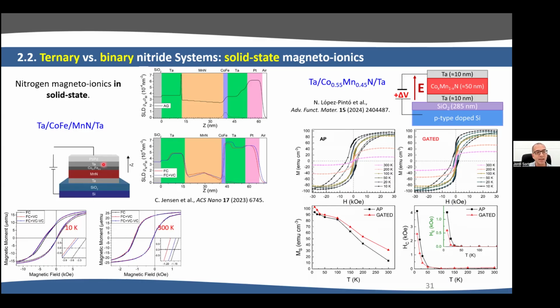And what happens here is that when you apply voltage, there are slight variations in the exchange bias. Okay, that was the first observation of modulating exchange bias in solid state in nitrides. And the reason for that is that when you anneal, there is some motion of nitrogen towards tantalum, because tantalum likes nitrogen a lot. And then when you apply voltage, there are slight changes in the concentration of nitrogen in the tantalum, and this nitrogen goes back to manganese nitride,